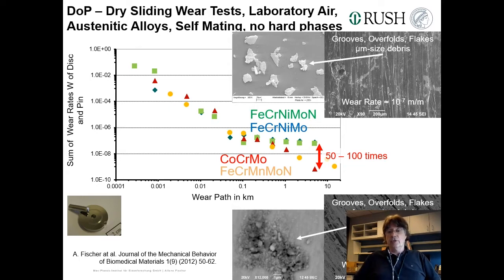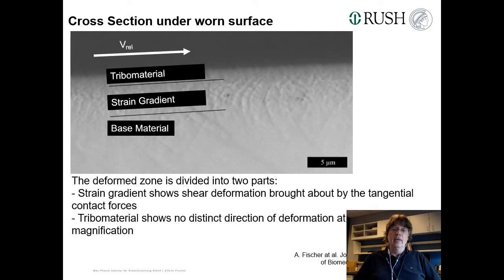The other two materials, also face-centered cubic, generated very, very tiny grooves. And again, they are attributed to microplowing, and you could still see some tribo-oxidation, so thick oxide films here, which were able to survive because the grooves were very, very small, and both of these materials generated nanometer-sized wear particles. Question is, why? So you make a cross-section, and I apologize for the blunt picture. It's the only one I had.